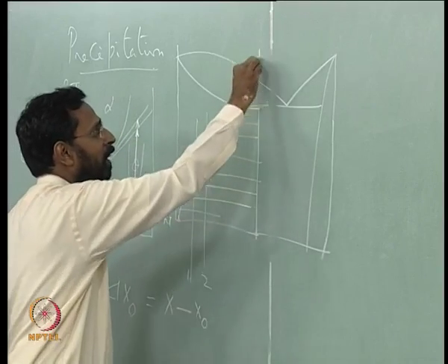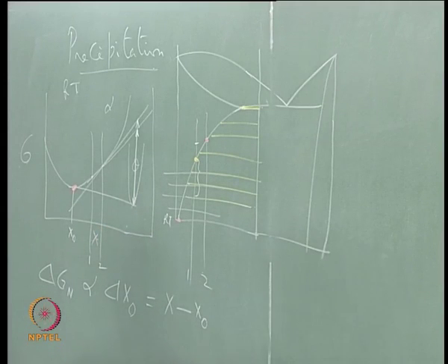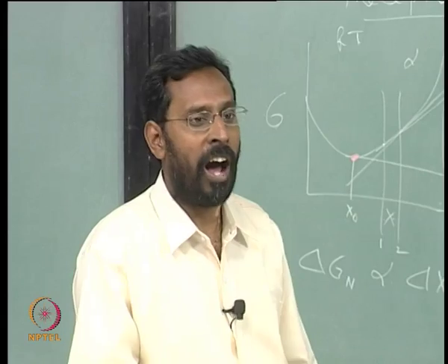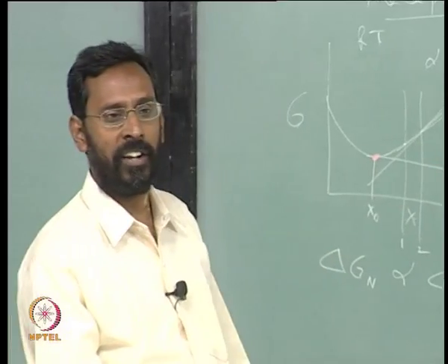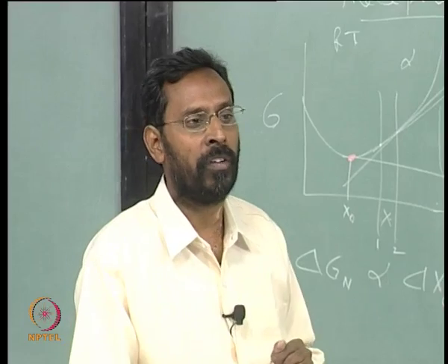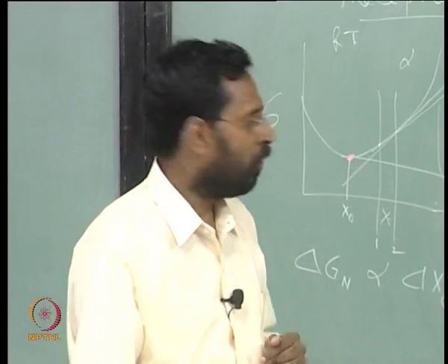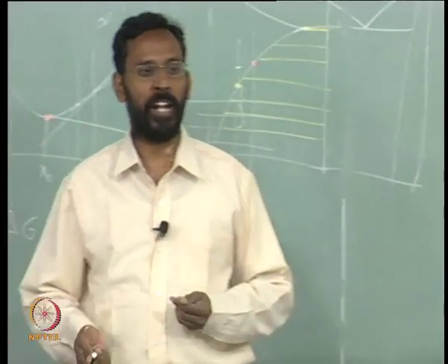So, this alloy, if I am solidifying it, how does it solidify first? It is a hypoeutectic alloy. So, what comes out first? Alpha dendrites come out first. So, you have the alpha dendrites, and once you reach the eutectic temperature, it is the eutectic mixture which comes out of the liquid. What is the eutectic mixture here? Alpha plus theta. So, at the dendritic boundaries, and these dendrites will get converted into grains later.